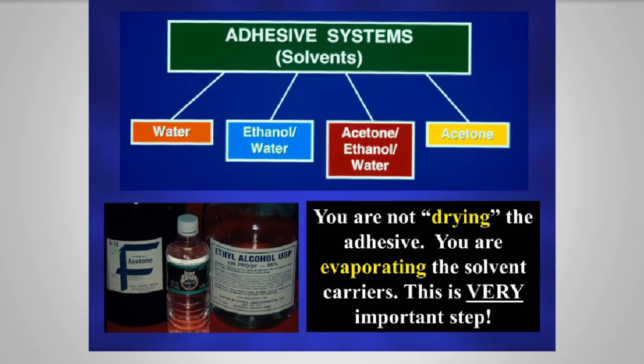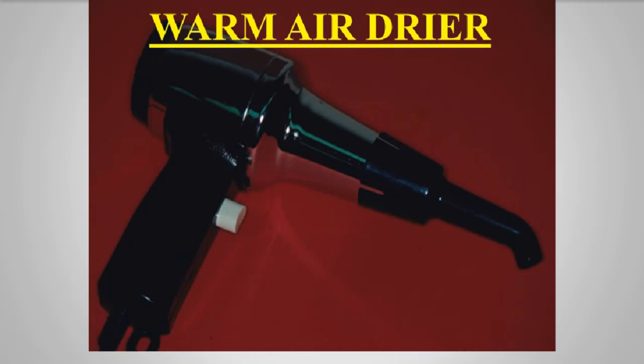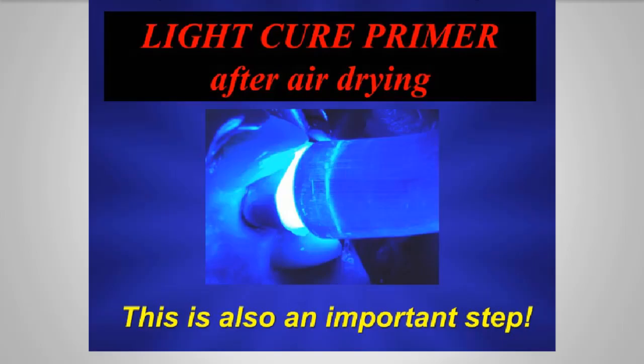Also, a very important step is to light cure the primer after you air dry it. The one caveat to that is for some indirect restorations with some dentin adhesives, because you have to worry about film thickness. But I don't think you should be using those anyway when you're using indirect restorations. I think you should be using adhesives that you can light cure and you don't have to worry about film thickness. And there's lots of them out there. But it's also, I think, a very important step. So just realize that light curing that primer is an important step.